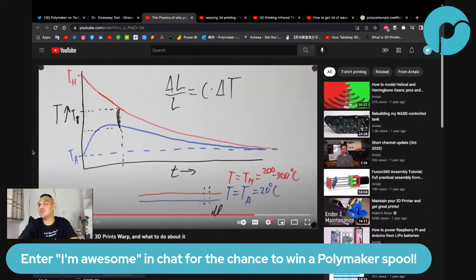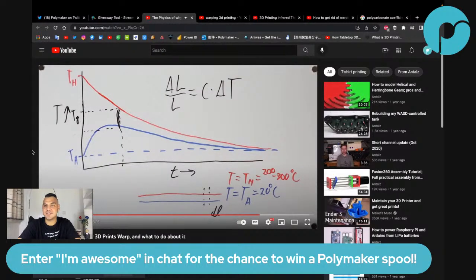So a material with a higher glass transition temperature is more likely to warp because the gap between the room temp and Tg is bigger. Yes, from his explanation. I also think that the higher the glass transition temperature, the worse it is, but for a completely different reason. And this is also what he thinks, but I don't think his explanation is logical. By the way, nylon's glass transition temperature is 60 degrees, but it warps way more.